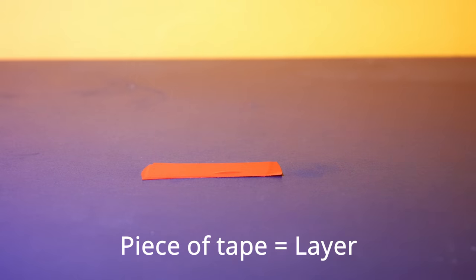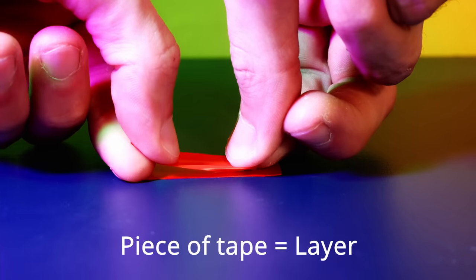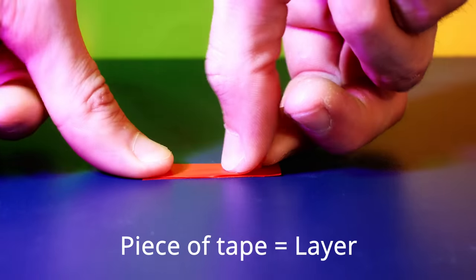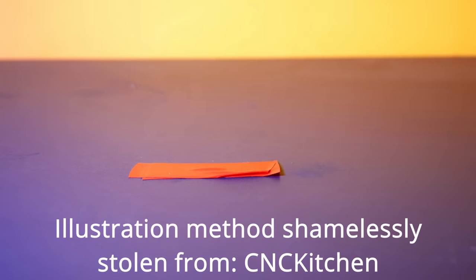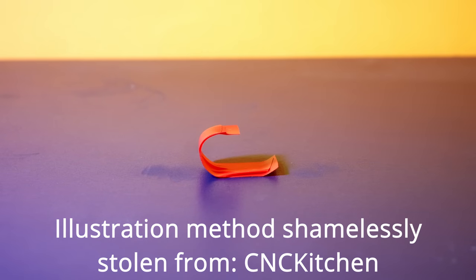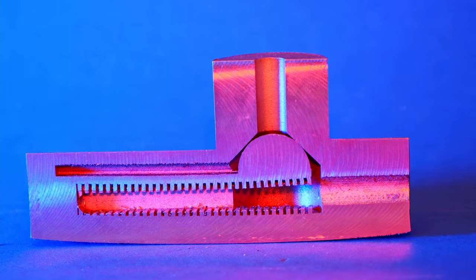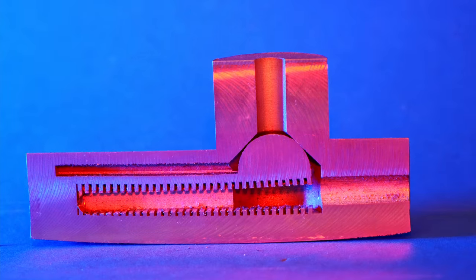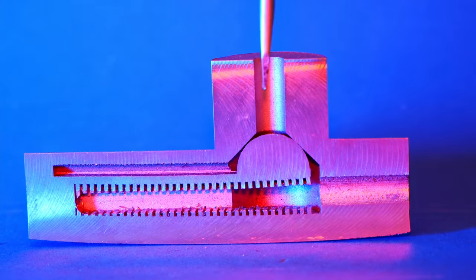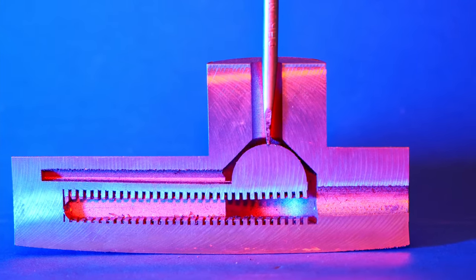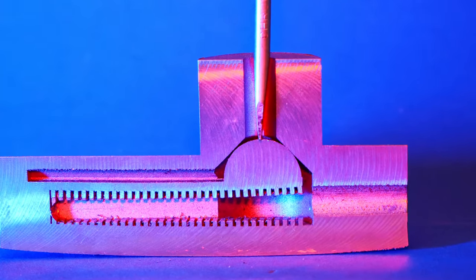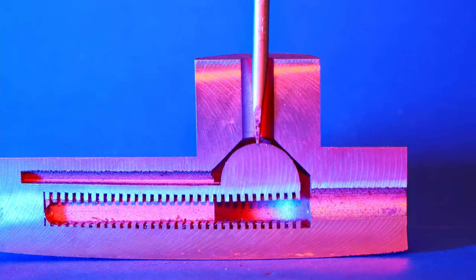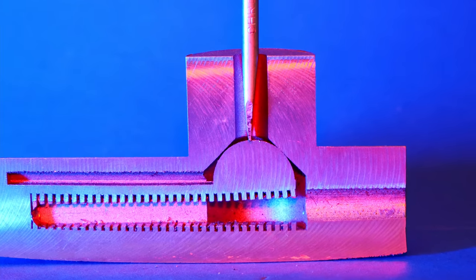This is very similar to warping in FDM 3D printing. These stresses can be imagined as tapes that are stretched and stacked on top of each other and create an upwards bend. When the support structures are removed, you end up with a cantilever that acts as a spring for the sealing body, and thereby we have created a spring-loaded check valve that is completely print in place.